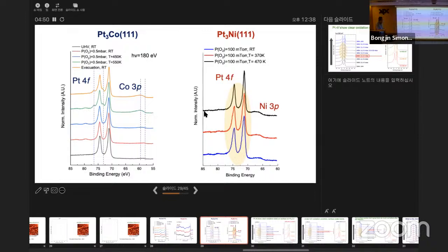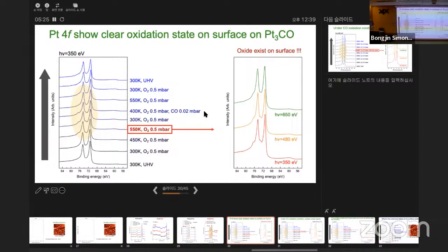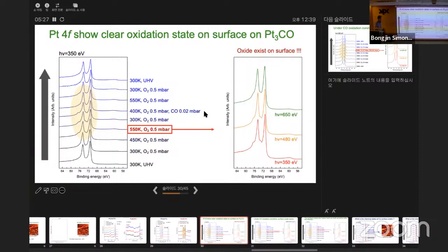But when you look at the platinum 4f, the platinum chemical state, for nickel, as I said before, when you form the oxide on the surface with the nickel oxide, the platinum still remains in a metallic state. But platinum cobalt, no, it's not. It's actually showing a clear oxidation state. And this clearly indicates that cobalt is different from nickel. The platinum nickel alloy is maintaining its own metallic characteristics, but cobalt is not. And so we were wondering where that is coming from.